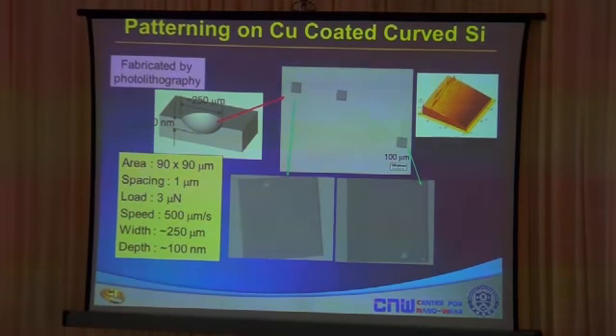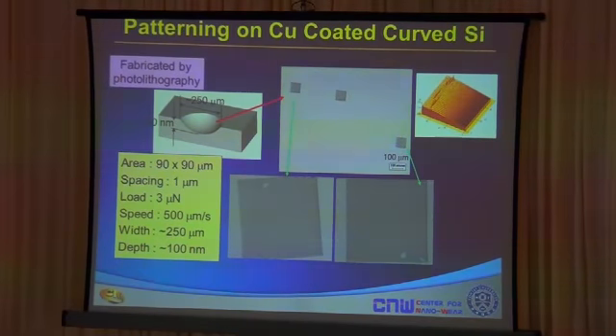Furthermore, we're able to make patterns on non-flat surfaces. When you're using photolithography with optics, one of the fundamental requirements is a very flat and smooth surface. If you don't have a flat surface, you will have problems in terms of patterning. You will lead to failures. However, because we're using an AFM tip with a feedback control which is able to follow the contour of the surface, we can make these patterns even on inclined surfaces, as you see here.